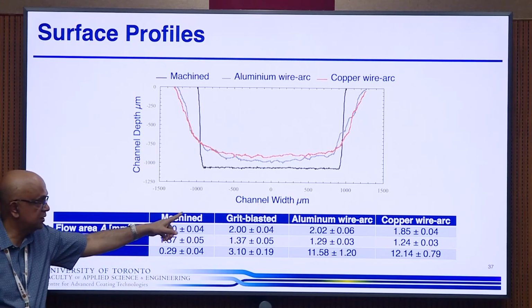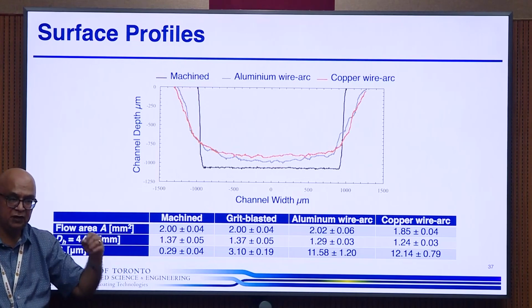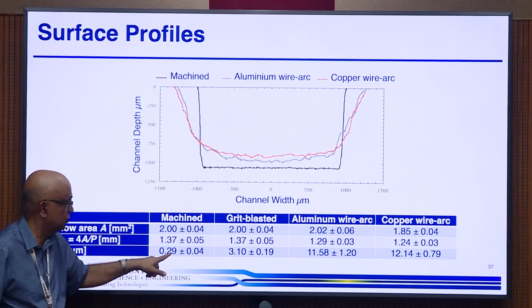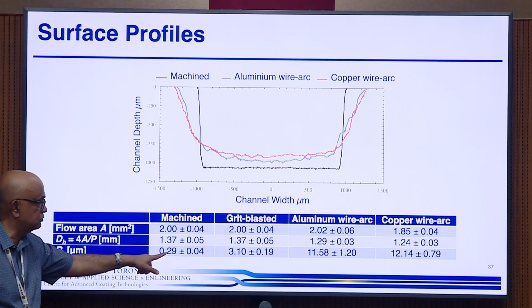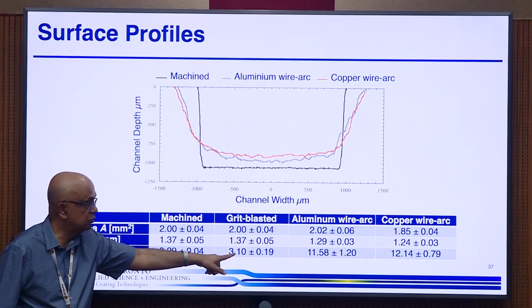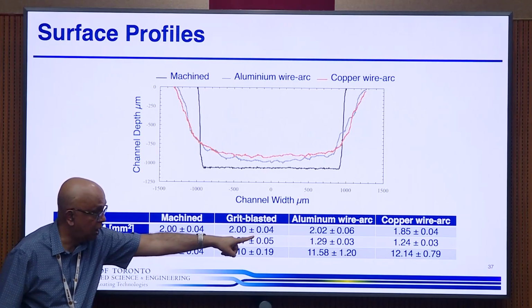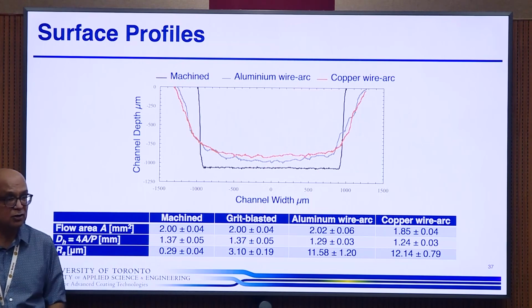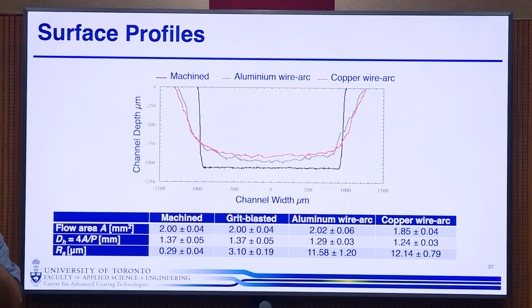The second machined one, we machined it and we grit blasted. So the surface roughness for this was about 0.2, this one about 3 microns. Our wire arc, you'll see, and the sprayed ones are both, the roughness is much higher.